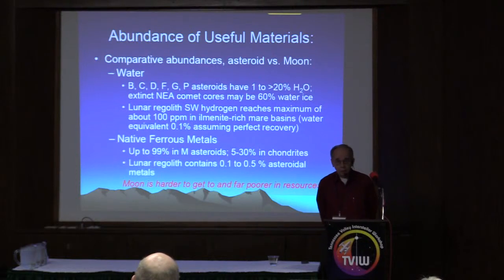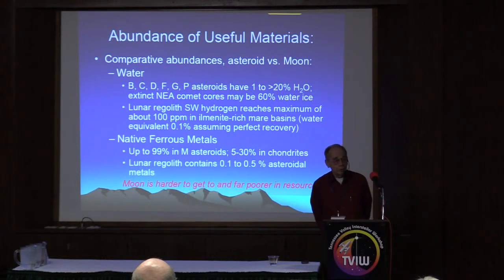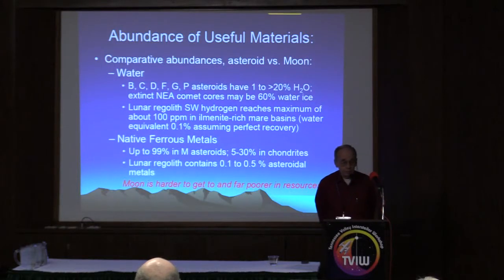Mostly carried by the mineral ilmenite, iron titanate, which is rich in the mare basins, the dark areas on the near side of the moon. That is equivalent, if you recover 100% of the hydrogen from the ilmenite and expel it as water, the hydrogen reacts with iron oxides in the ilmenite and other minerals to produce water, and will provide up to the equivalent of 0.1% water if you get perfect recovery of the hydrogen.